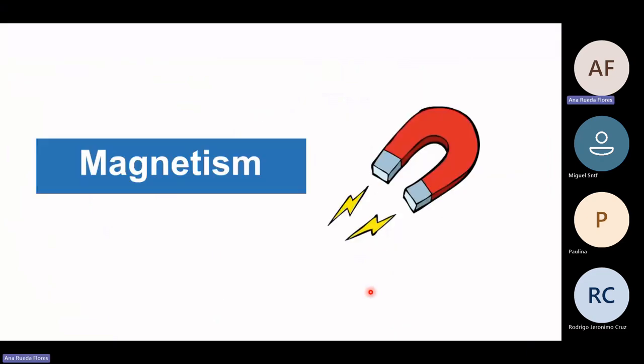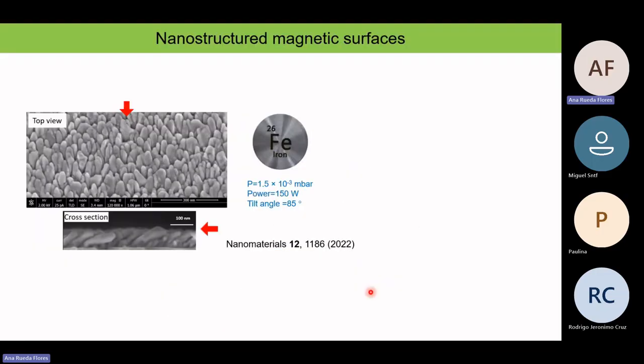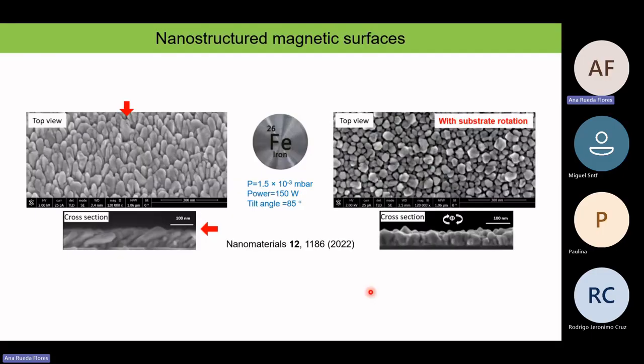And the final application is in magnetism. In this case, we will work with iron. We can fabricate tilted iron nanocolumns, or we can rotate while we are depositing, and then we can have vertical iron pillars. And these two materials exhibit different magnetic properties.